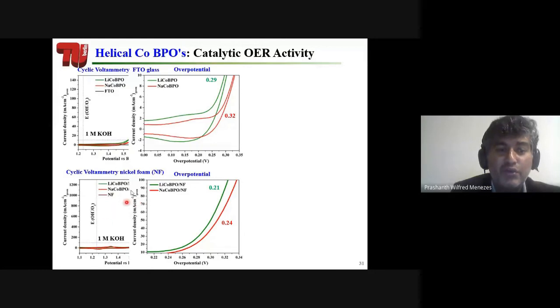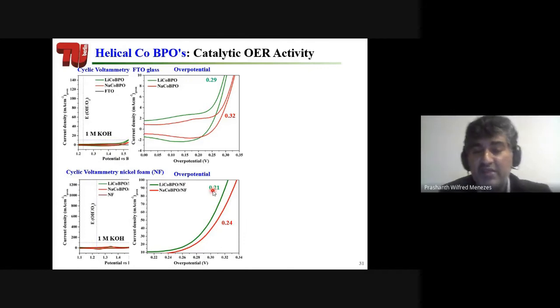We also show you on FTO glass and also from nickel foam. You see that on nickel foam, the overpotential is rather decreased. That means we have a better activity on nickel foam. This is because of the electronic conductivity of the substrate. Nickel foam is electrically very, very conducting. So therefore, we have better activities.